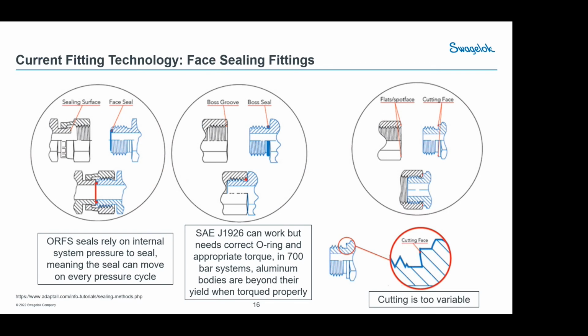Two more pop up, and the first one is going to be the O-ring face seal. So an O-ring face seal is one flat face, a fitting in a groove. They have an O-ring, could be a quad ring, could be a couple of different designs. We understand this very well. The first patented O-ring face seal was actually Swagelok's VCO fitting back in the 60s. It's been copied a lot since it's come off patent in a lot of different ways. This became a very popular fitting design for natural gas vehicles, and then fairly soon after that, it got removed from a lot of the natural gas vehicles because it leaks. The O-ring moving within that particular surface.